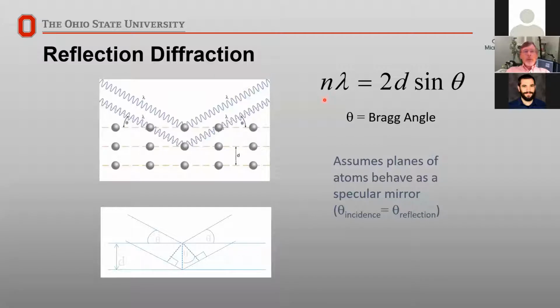So now we normally will set n equal to 1. We know what lambda is, that's our wavelength. We can measure the angle where the peak is, and that tells us the d spacing, or the spacing between the planes. And from that, then, we can get a fingerprint of the crystal structure.